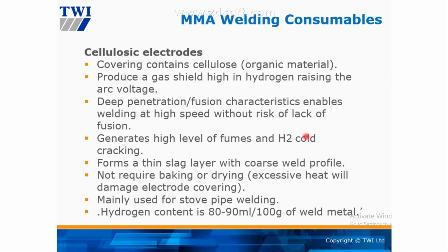I would like you to highlight a few things here. The first thing we are talking about is cellulose. Please highlight this level of hydrogen. We have between 80 to 90 milliliters of hydrogen. So what is the advantage of having very high hydrogen in cellulose? If we have high hydrogen, it will raise the arc voltage, meaning it is giving more heat, increasing heat from having this hydrogen.